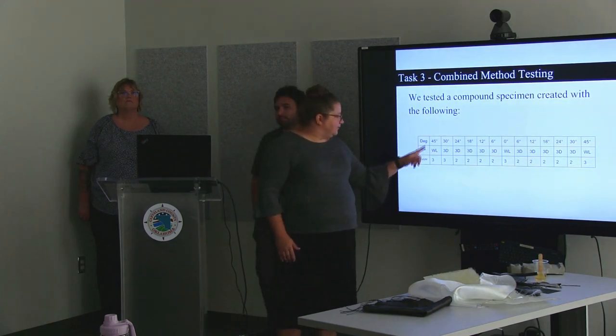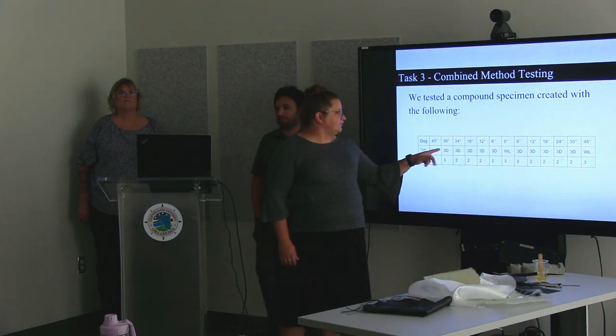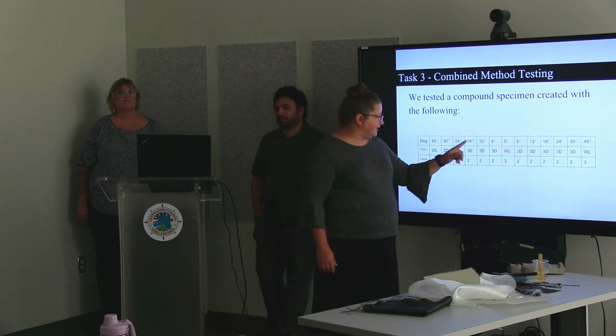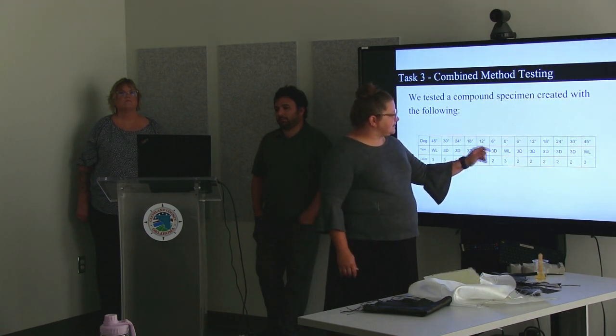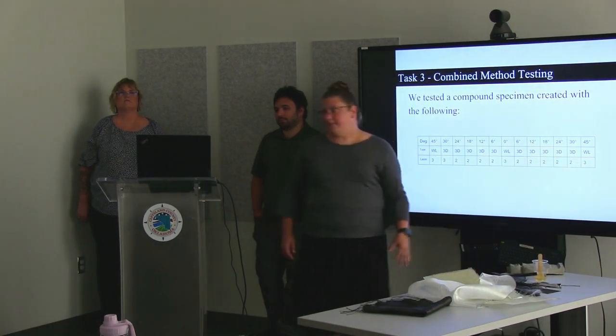So we used wet layup for our 45 degree angles, 3D printed our 30, 24, 18, 12, and 6, and then another wet layup for our 0, and mirrored it on the other side.